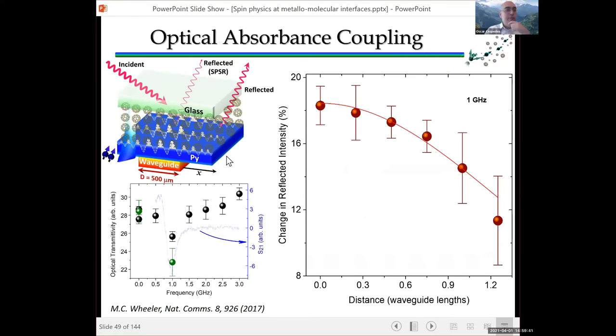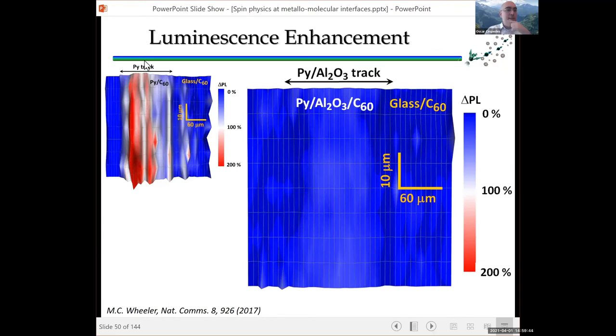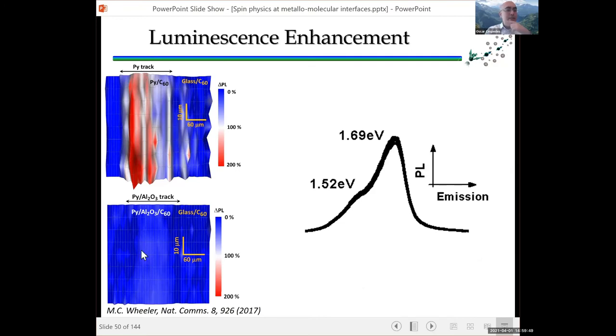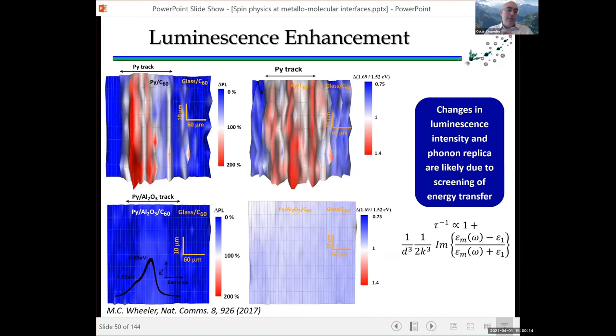So you can see you have about 200% enhanced optical luminescence in the C60 during resonance, and that enhancement disappears when you separate the C60 and the ferromagnet with an alumina layer, or when you measure the C60 on the outside of the ferromagnet. So that's a luminescence enhancement due to the spin pumping. And the reason you have that enhancement of the luminescence is that the spin current is destroying the dipole at the interface and reducing the non-radiative energy transfer from the molecule dipole to the metal. Okay, thank you so much.